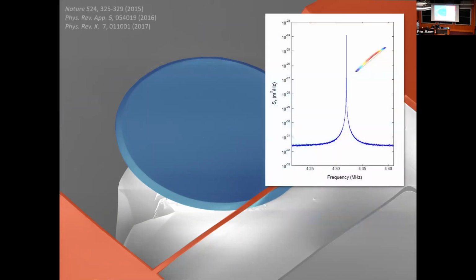So if we use that technique to make very sensitive measurements of the displacement of this little mechanical resonator, sufficient to resolve its thermal motion with a signal to noise of something like 10 to the 8. So what you're seeing here is the thermal force being amplified by the mechanical oscillator. And it looks Lorentzian because that's the shape of the susceptibility of a damped harmonic oscillator.